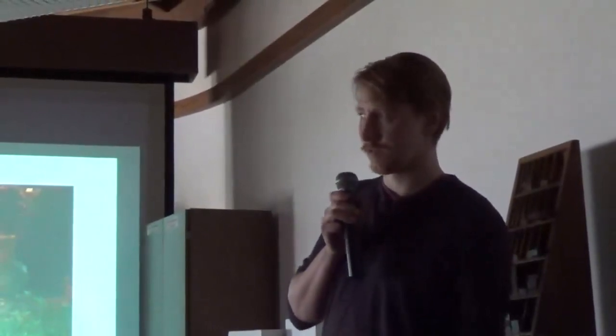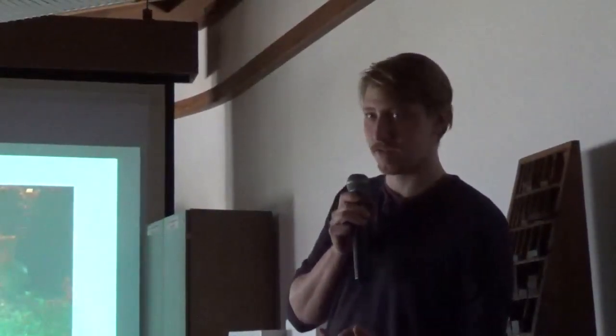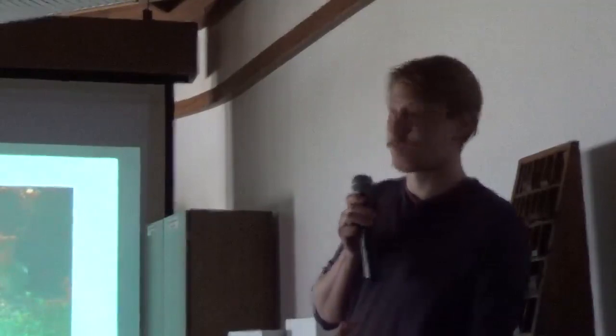Sometimes this just happens. And so it hadn't really gone up too high in temperature. It was about 800 degrees or so. So I shut the kiln off, waited for it to cool a little bit, and I pulled that piece out, and I poured more slip back on it and threw it back in the kiln. While it was warm? While it was warm.